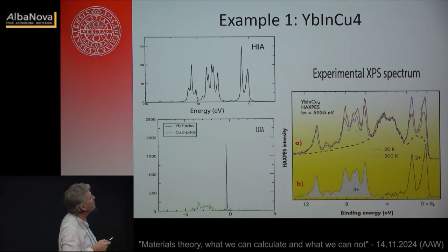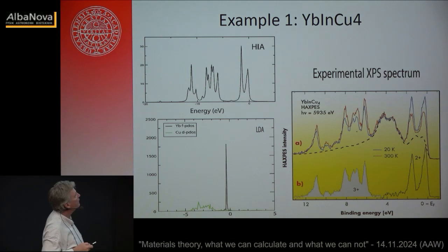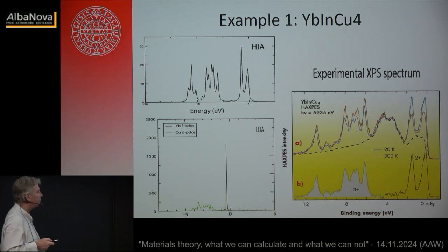And there are photoemission measurements on this material, plotted over here. In the experiments, they were able to extract what came from copper and indium to identify the contribution of the 4f shell. And don't ask me how that was done, but they did. And then they came to this experimental spectrum and said, this is now the spectrum that comes from the 4f shell of the ytterbium atom in this compound.